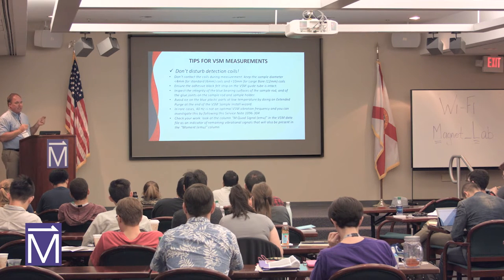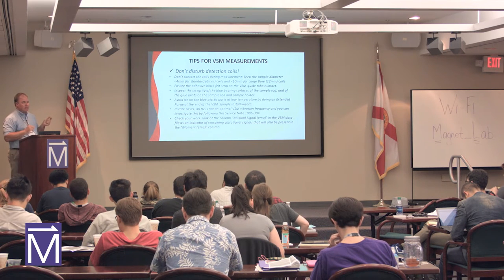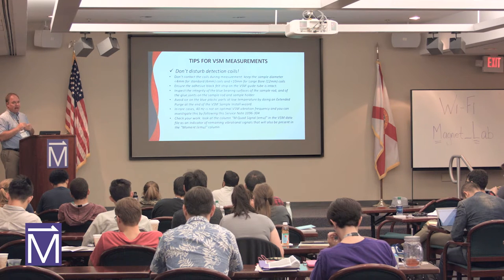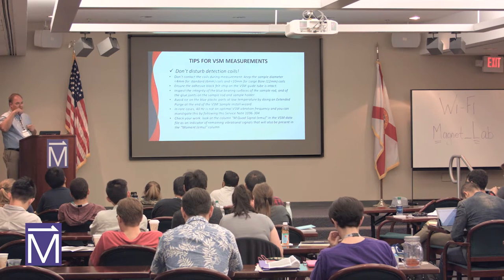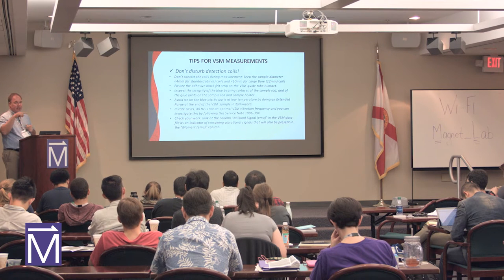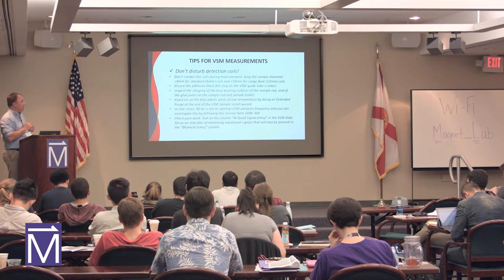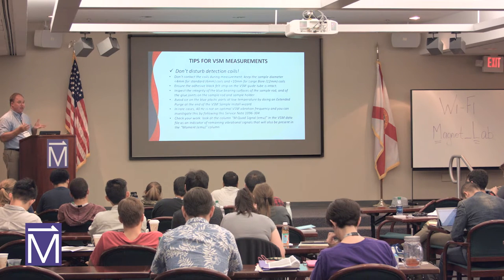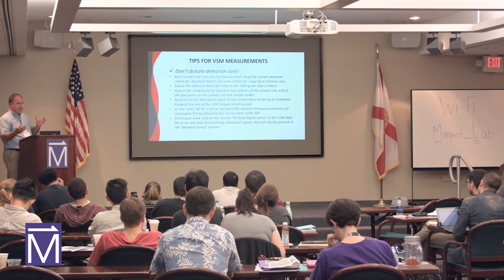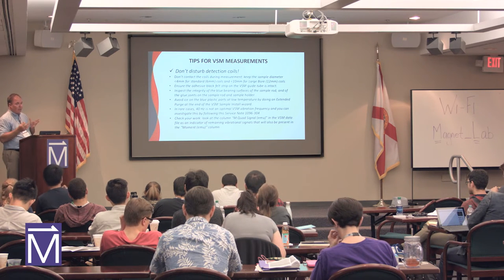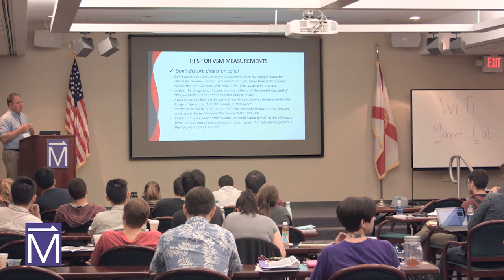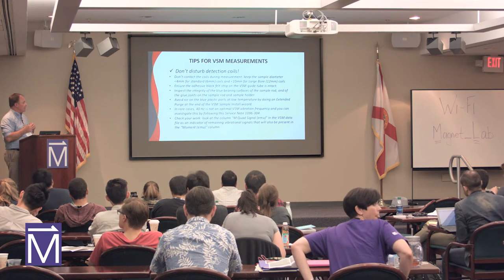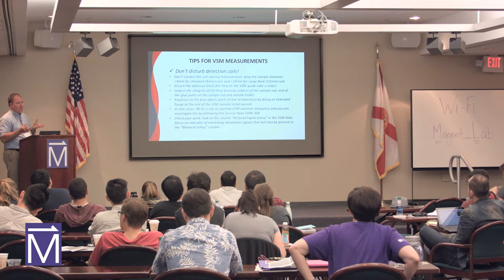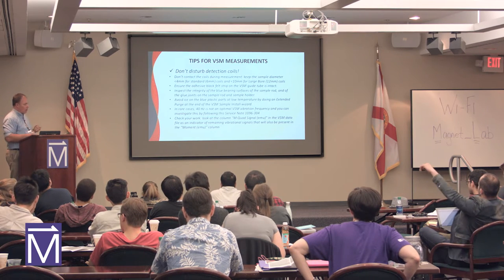The common source of this error is some ice that forms in the system, so you didn't purge the system out enough. Ice will form on a couple of the parts on the sample rod, and those will touch the coil and cause an artifact. So you need to make sure your sample's not outgassing, not absorbing atmosphere and then freezing into the system. Those are some things you may want to check, and check the high vacuum of the system so that there's no ice forming.